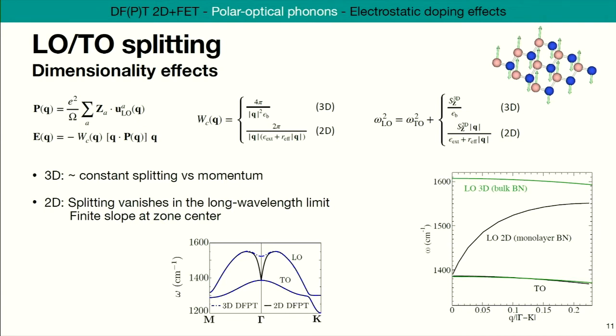So I've already talked about those polar optical phonons, but just to give a quick summary, they are present in any material or semiconductor with more than one kind of atom. That's because different atoms carry different effective charges, and when you move them with respect to each other according to a phonon displacement pattern, you're going to generate some little dipoles. And those dipoles are effectively represented by a polarization density that we see here.